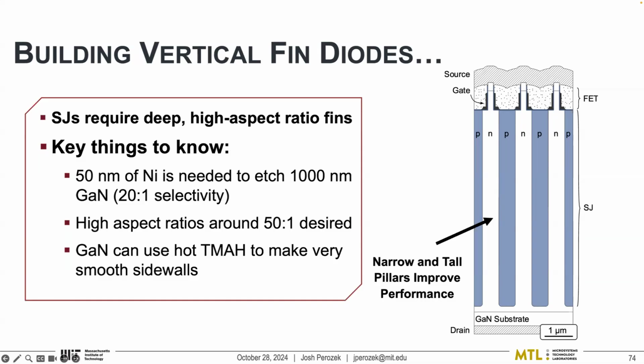And then the last thing, unrelated to that, is for all of our fin fabrication, we do have one big advantage in GaN: we have crystallographic wet etchants. So if we use TMAH, we can actually align the fins to the right sidewall. And no matter how dirty our etch is, if we use this wet etch treatment, we can make almost atomically smooth sidewalls in our gallium nitride.